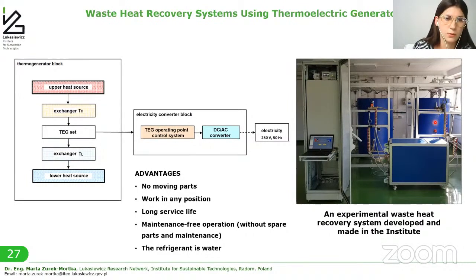Consequently, it can be used to extract heat from sources with different temperatures, and the maximum temperature for heating the liquid in the tank is set at approximately 95 degrees for water, which stores the heat energy, while the minimum temperature for cooling the liquid is 4 degrees. Similarly, the storage and heat exchange modules with low thermal parameters are adapted to cooperate with different heat collection systems, an example of which is a dry or wet cooling tower, fanless cooling tower, or an adsorption aggregate.